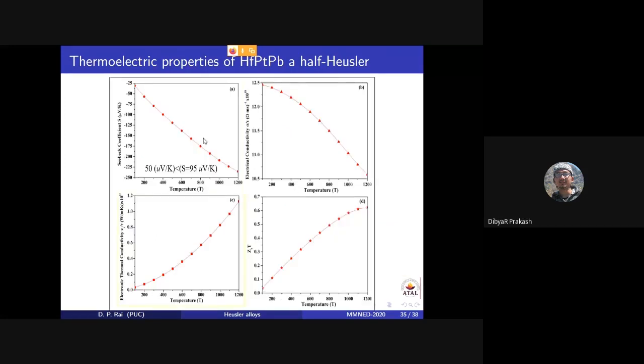The electron part of the thermoelectric parameters for this HfPtPb Heusler alloy has been calculated by the BoltzTraP code, which is based on the Boltzmann semi-classical transport equation. This is the Seebeck coefficient we have calculated as a function of temperature, and this is the electrical conductivity as a function of temperature. This is the electron part of the thermal conductivity, because the thermal conductivity has two parts: one is the lattice contribution, and the other is the electronic one. And this is the ZT, the efficiency, that we have found, and you can see that the ZT value increases with the increase of temperature.